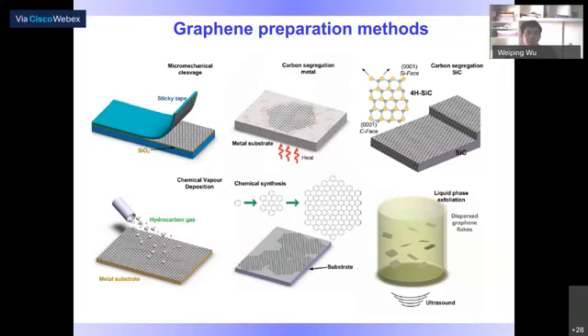But they tend to be quite complicated and quite expensive, or the sample size is relatively small, so they can't be produced on a larger scale. In reality, using these methods, you can only get a very tiny amount of graphene, which only allows you to prepare samples in the lab. So that hinders further development and industrialization of graphene. Therefore, I developed a solution process, or liquid phase exfoliation, of graphene.